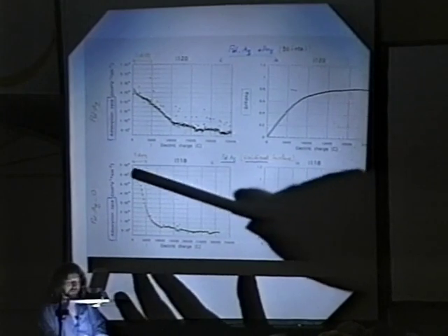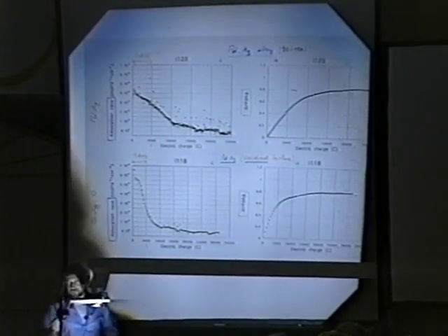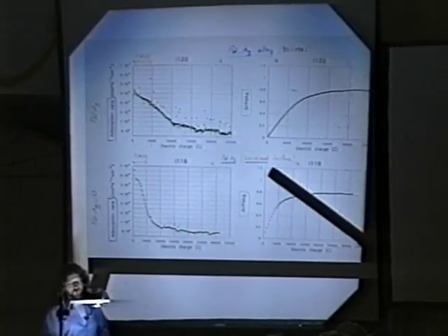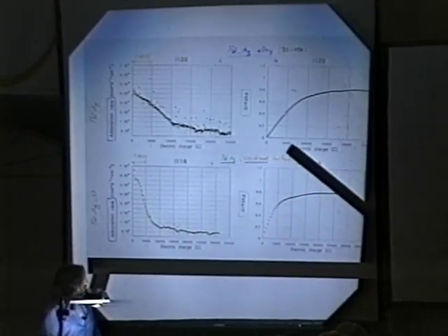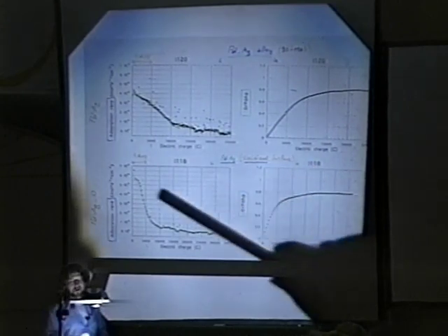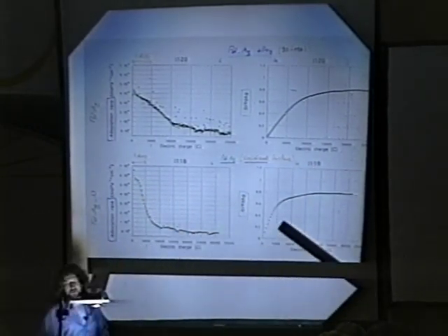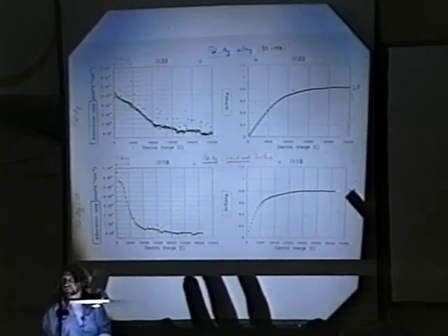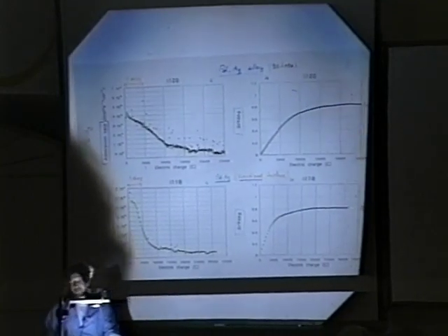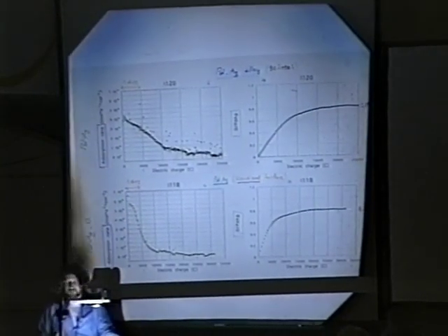So this is exactly the same, not the same. Another plate, another palladium silver alloy, was oxidized on the surface, and it shows the same dynamics. The loading ratio is more or less the same. It happens because the silver inside, the 10%, is a lot.